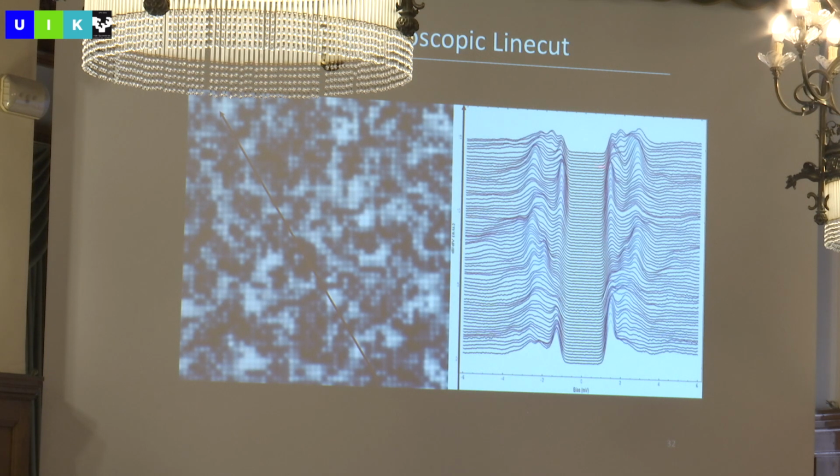And these coherence peaks, the reason you have multiple coherence peaks is because you have all of these pockets. You have these electron pockets and the hole pockets. Each pocket has a slightly different gap. And that's why you see these multiple coherence peaks.